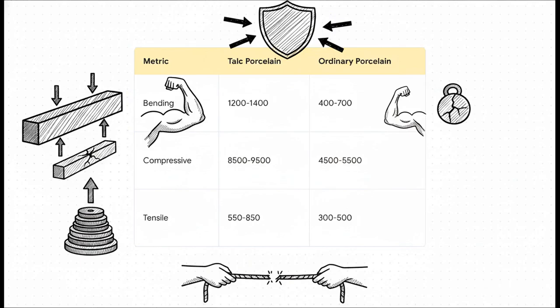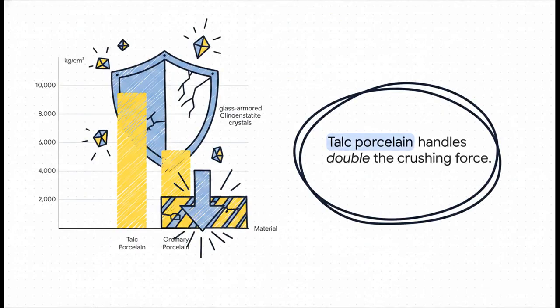If we talk about bending strength, it goes up to 1,400 kilograms per square centimeter compared to just maybe 700 for ordinary porcelain. Its tensile strength, meaning its ability to be pulled without snapping, is nearly double. And the contrast in compressive strength is just as staggering. Talc porcelain reaches up to 9,500 kilograms per square centimeter. I mean, this material can handle almost double the crushing force of standard everyday ceramics. Those glass-armored clinoenstatite crystals do exactly what they were engineered to do.